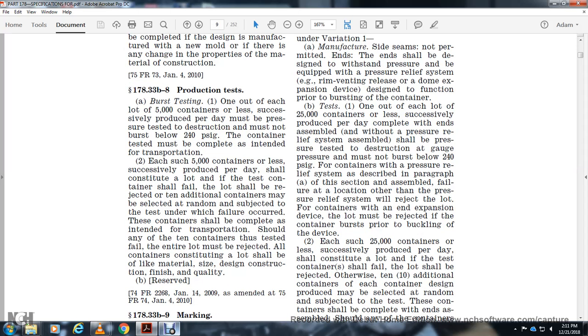178.33b-8 Production testing. Burst testing. One out of each 5,000 containers or less successfully produced per day must be pressure tested. Tested to destruction and must not burst below 240 psi. Containers tested must be complete as intended for transportation. Each 5,000 containers or less successfully produced per day shall constitute a lot. If any of the tested containers fail, the lot shall be rejected, or 10 additional containers may be selected at random and subjected to the test. If failure occurs with any of the containers, the lot shall be rejected. Should any of the 10 containers fail the test, the entire lot must be rejected. All containers that constitute a lot shall be alike in material, size, design, construction, finish, and quality.